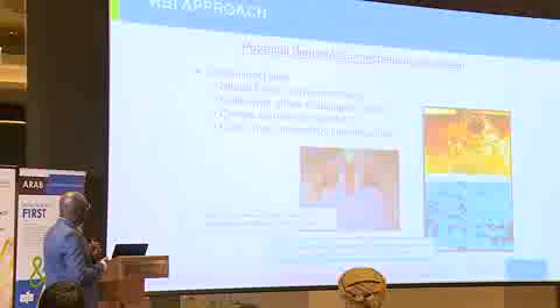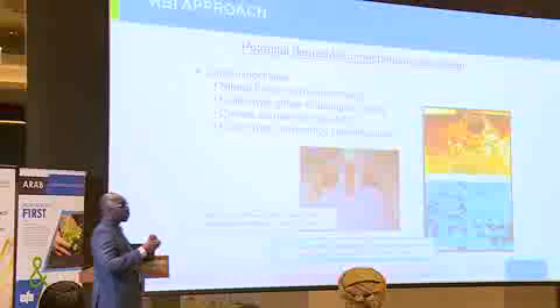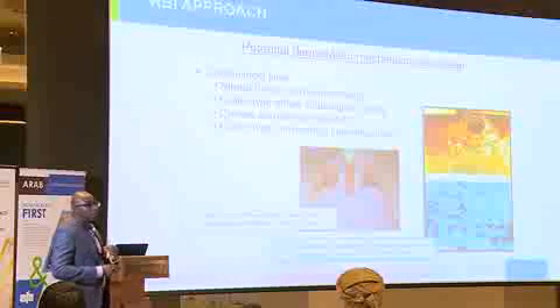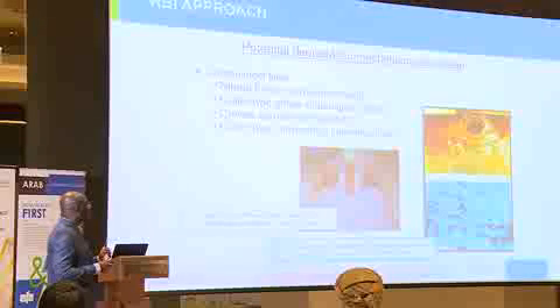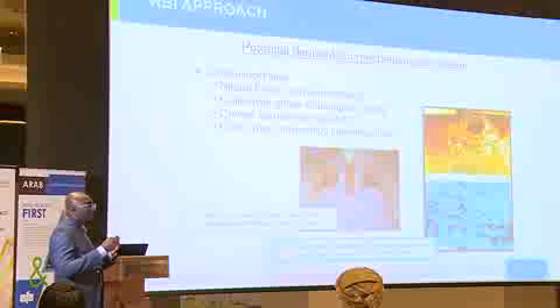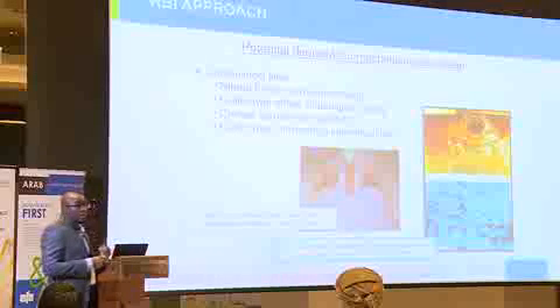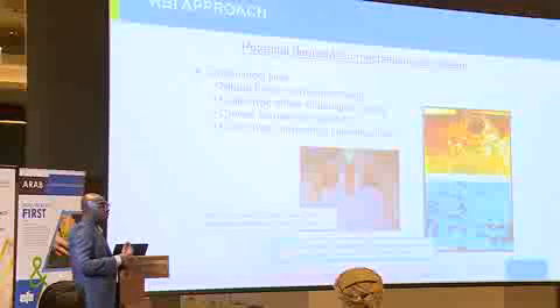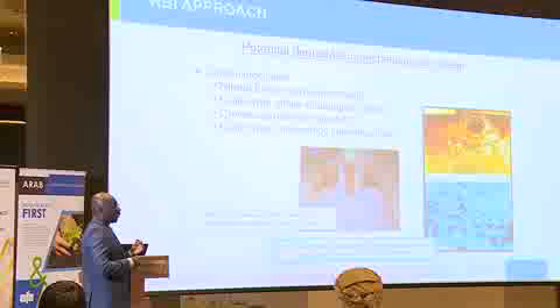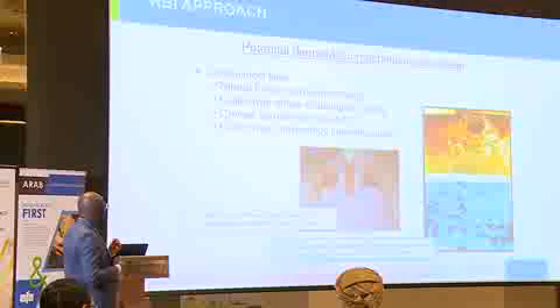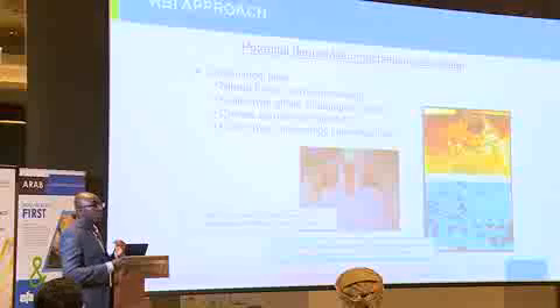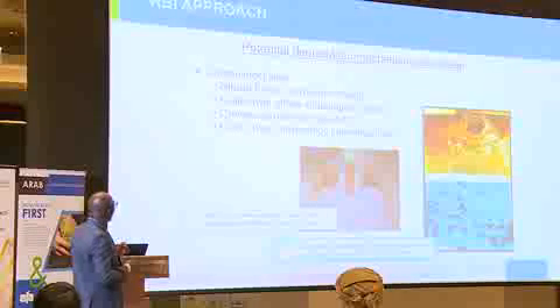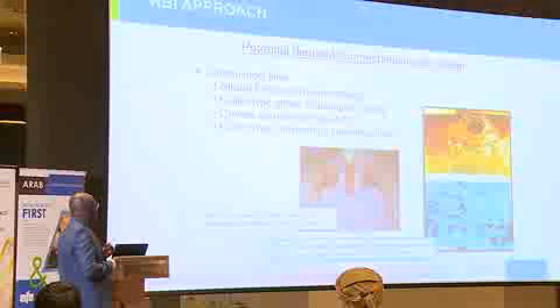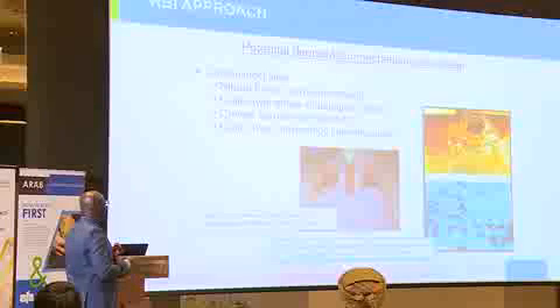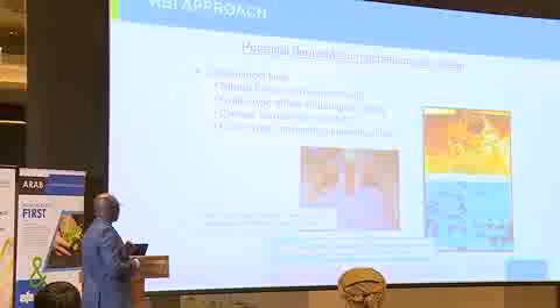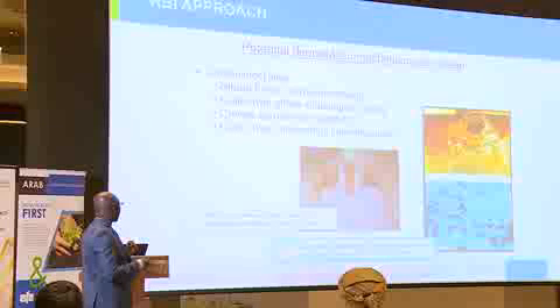So you can have nitrate stress corrosion cracking, because urea plants, just based on where they are, close to ammonia plants and then other installations in the neighborhood, you have a lot of nitrates in the atmosphere. And then when you have rainfall or even water from your firefighting drills, or just dew falling at night, or breathing vents, these can all get nitrates into insulation if you don't have proper insulation and jacketing. You can also have crevice type attacks on damaged coating, which is why when you want to repair this, proper surface preparation is important. We can talk about crevice corrosion at supports, and then crater type supports by intermittent use.